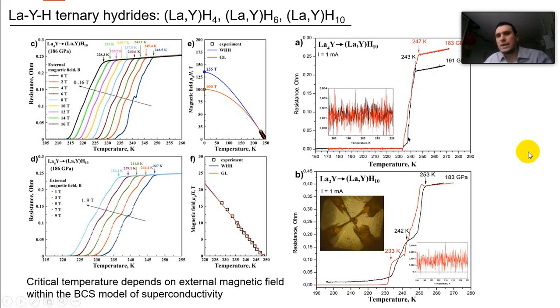Transition can be very narrow, about several degrees. Here it's a bit longer, a bit wider. And in the magnetic field, you see the transition actually shifts to the left side according to the normal behavior of superconductors. When we apply an external magnetic field, it suppresses superconductivity, and it occurs at lower temperature than it should be without magnetic field. So the upper critical magnetic field can be estimated using different extrapolation models.